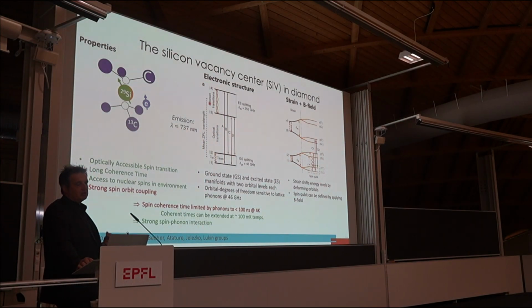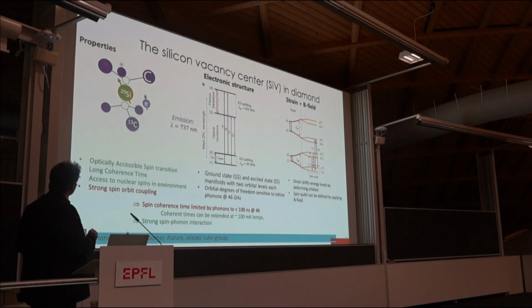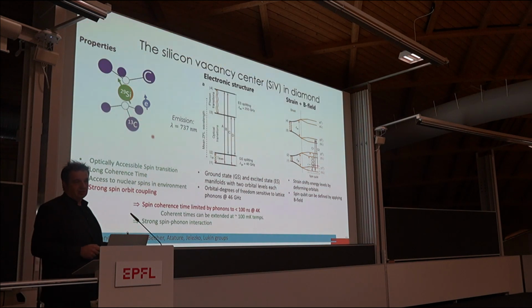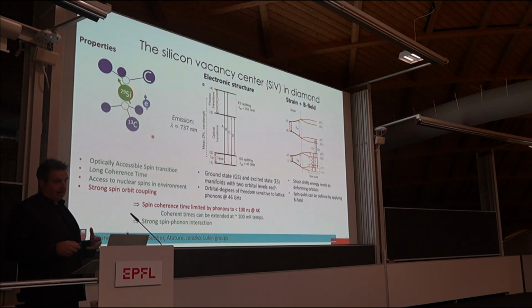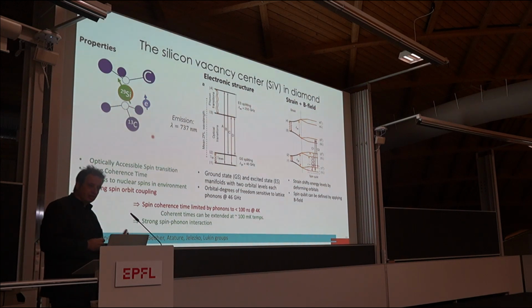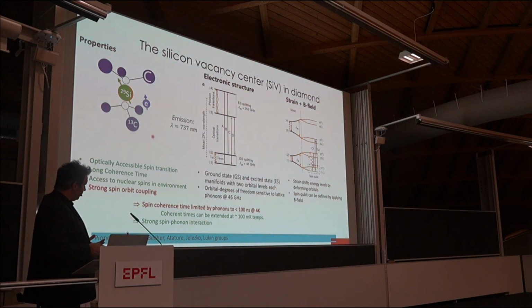In our lab, we focus on the silicon vacancy color center in diamond. So this is a silicon atom that sits between two vacancies in the diamond carbon lattice. And it's nice because it's not sensitive to charge fluctuations in the surface to the first order. It also doesn't have a Stark effect, which is a problem when you need to tune it, but I'll show you some examples of how to tune it.